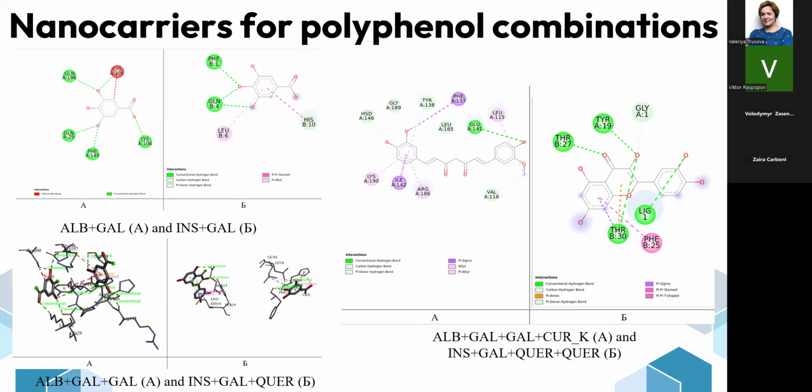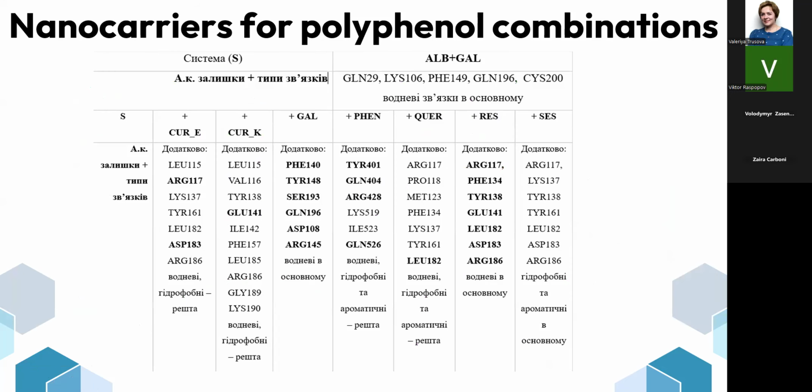It is clearly seen that hydrogen bonds represent the predominant bonds that stabilize the protein-polyphenol structure. However, other interactions such as aromatic or hydrophobic are also present, but for all complexes, this hydrogen bond, which is highlighted here in green, represents the main force for stabilization of polyphenol-protein complexes.